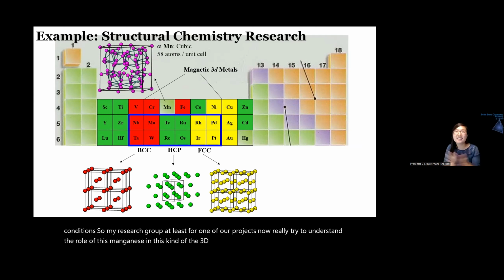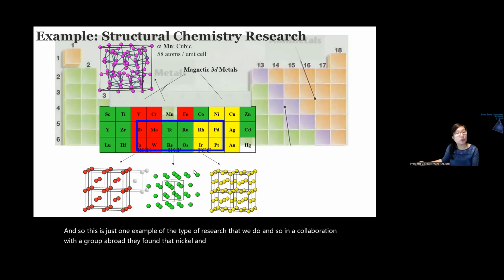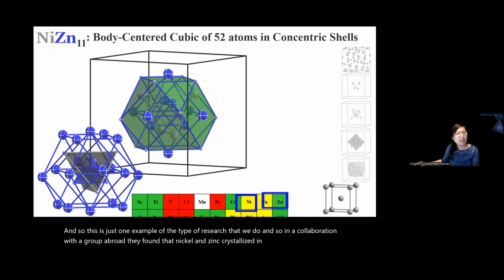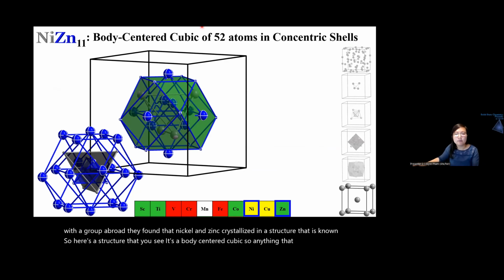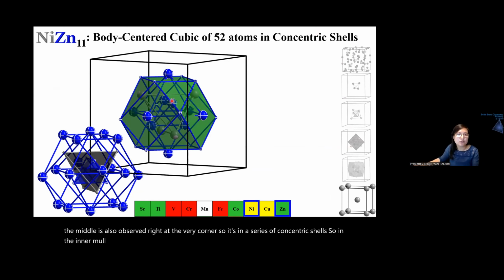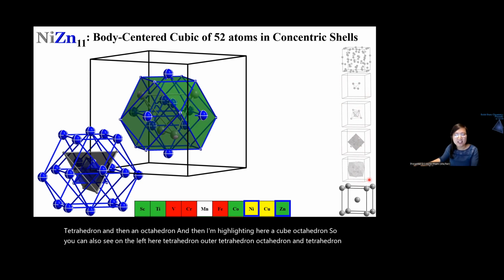And so this is just one example of the type of research that we do. In a collaboration with a group abroad, they found that nickel and zinc crystallize in a structure that is known. So here's the structure that you see. It's a body-centered cubic. So anything that you see right in the middle is also observed right at the very corner. So it's in a series of concentric shells. So in the innermost shell, we have an inner tetrahedron, then an outer tetrahedron, and then an octahedron, and then I'm highlighting here a cuboctahedron. So you can also see on the left here, tetrahedron, outer tetrahedron, octahedron, and cuboctahedron. And then it's a body-centered cubic.